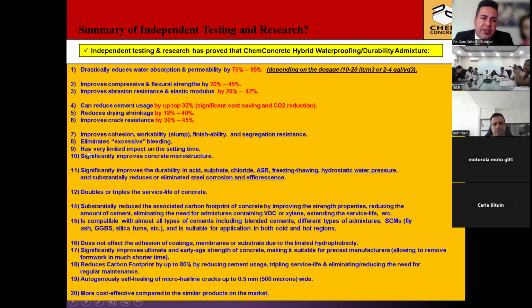Eliminates excessive bleeding, has very little impact on the setting time, significantly improves concrete microstructure, and has almost no impact on the heat of hydration. It significantly improves durability in acid, sulfate, chloride, ASR, freezing, thawing, and hydrostatic water pressure.